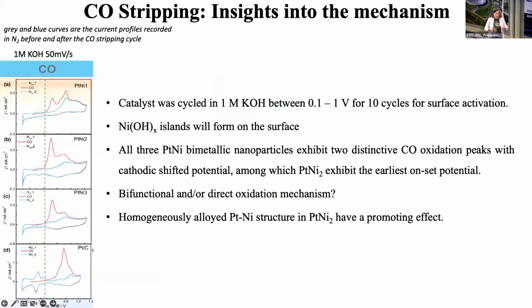Now we wanted to gain insights into the mechanism. So I told you about CO stripping and how it works. We did this for all the catalysts, pure platinum, and then all 3 of them. And again, I think our focus should be on this because it seems to be working a lot. So what we did, we cycled the catalyst in KOH between 0.1 and 1 volt for 10 cycles. And we did that to activate the surface.